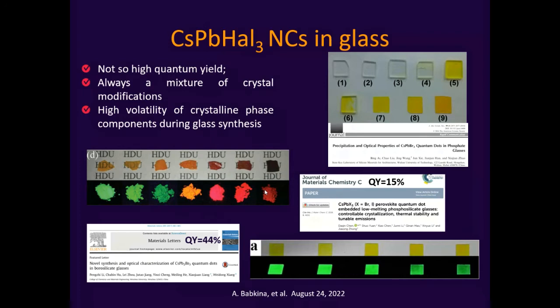And it's very suspicious, you know, that very highly luminescent nanocrystals inside of the glass, are they luminescent indeed or not? So after that, other papers arrived, this one and this one. And as you can see from the slide, the maximum quantum yield achieved was 44%. Yet it's twice less than 100%, you see. But these nanocrystals are in glass, and they're fully 100% stable, as the glass can be stable itself.